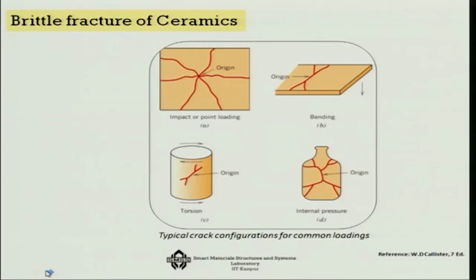Now, these are some pictures that show various types of brittle fractures in ceramics. If you had an impact or point loading on a ceramic tile, say, you will see that this is the way the cracks propagate, or if it is bending, you would see that this is the way the cracks propagate. If it is a torsion, you will see it at a 45-degree angle, which you will see in any strength of materials course, because that is the principal plane where the failure is occurring in tension. And if it is due to internal pressure, you would see this type of a failure. So, by looking at the failure, the crack can actually give us an idea of whether this has happened due to impact, bending, torsion, or internal pressure. For prognosis, that is very important.